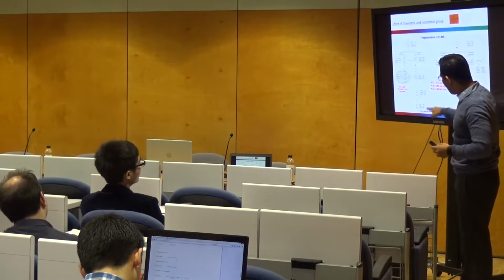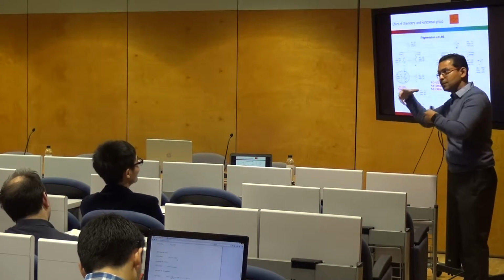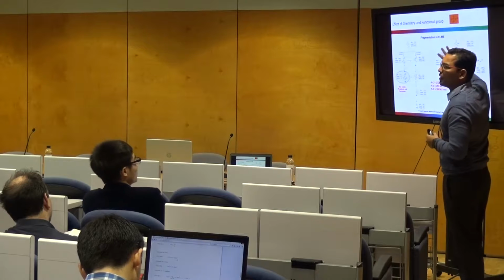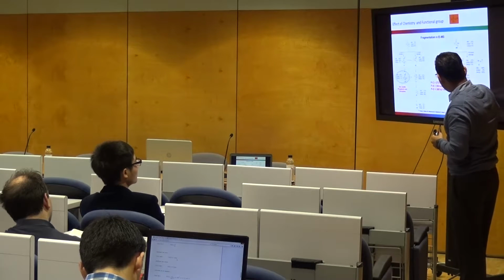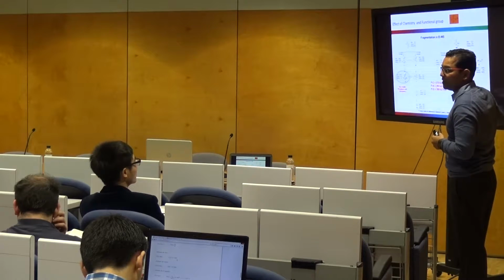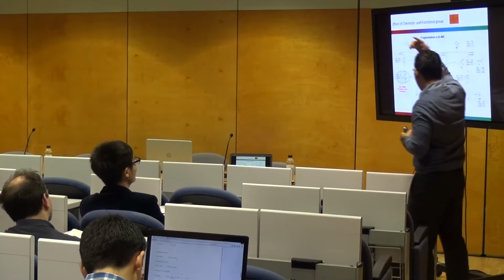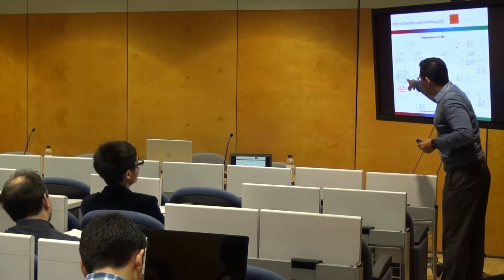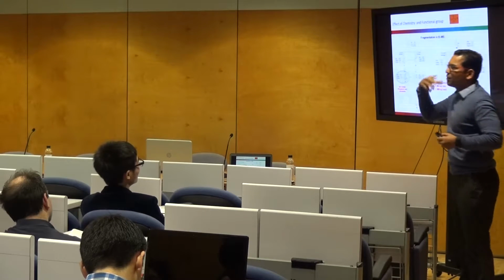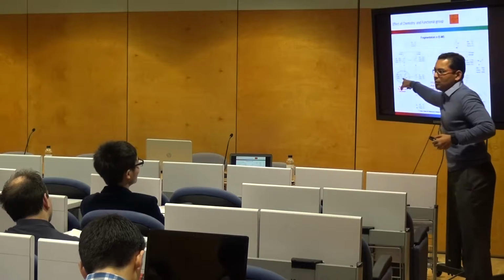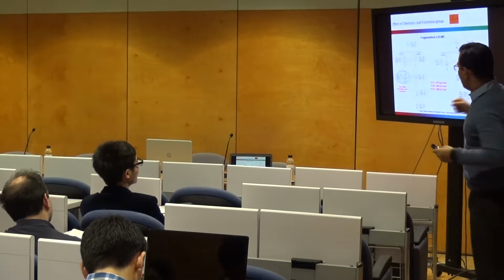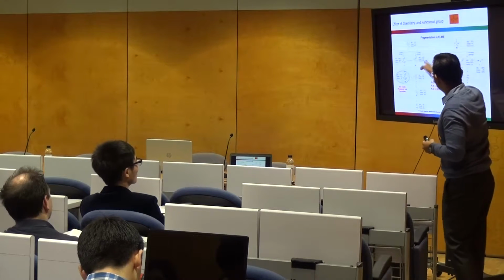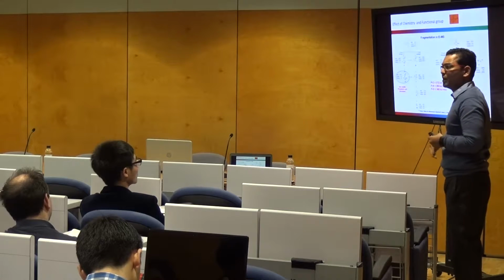Okay, the key fragment you look at is the PO fragment, which is supposed to do the flame retardant action. We found out for phosphoramidate and phosphonate, it was very efficient in getting these PO species, quite efficient in the fragmentation pattern. However, in case of phosphate, we also saw an additional pathway which was more or less like an acid. If you look at the phosphoric acid, it is very similar in structure here, I would say, what I'm trying to show. So the key difference was the fragmentation pattern of phosphate compared to a phosphoramidate and phosphonate were quite different.